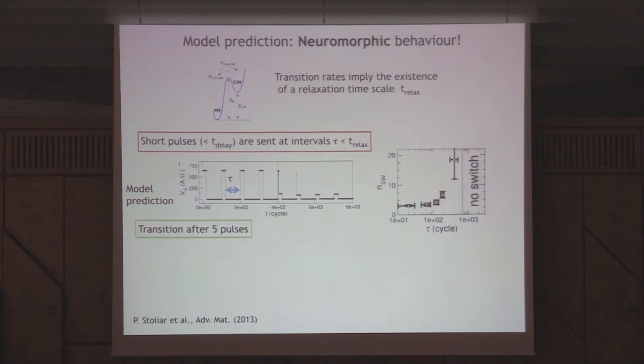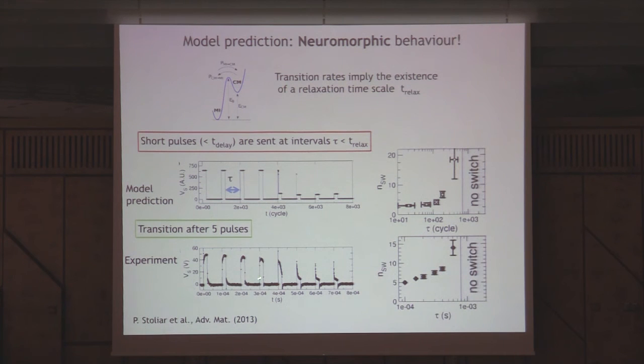So this was our clean-cut prediction, and then Pablo Stoliar, who was working with me, but is originally an electronic engineer, went to the lab and prepared the experiment by himself and did the experiment. And these are the experimental results. You have 1, 2, 3, 4, and then in the 5th pulse, you see the very fast transition to the low resistance state, and you can do that systematically and see that this clearly behaves as our prediction, therefore validating the model.